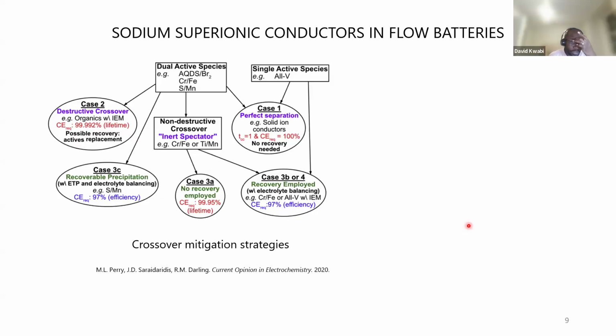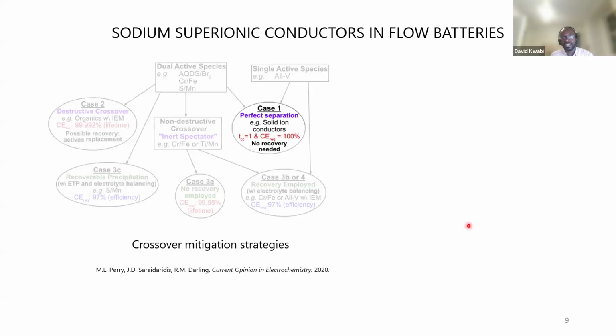So for the past 3 or 4 years, we've been playing with this idea of, rather than using typical polymer membranes in these flow batteries, using ceramic ion conductors. What's attractive about them is that they would bring about perfect separation between the negative and the positive electrolyte, because these are fully dense, hard ceramic materials that only permit, for example, a sodium or a lithium ion to cross from one side to the other. In principle, we would have no crossover-induced capacity fade.